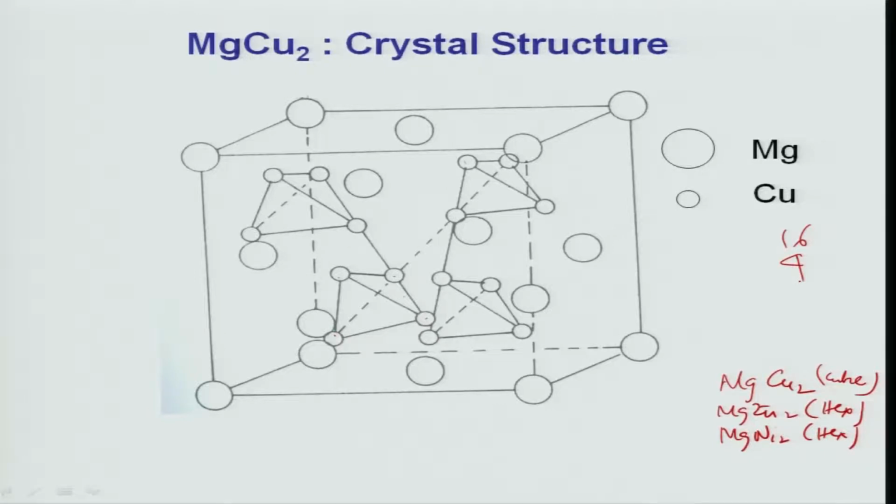But you have to understand that out of these 16 atoms, 8 atoms are for the unit cell, other 8 are not. So that is why it is 8 by 4, that is why it is MgCu2. Cu is 8 atoms and 4 atoms are magnesium. So this is the first type of structure, and there are many compounds like TiBe2, AgBe2 and BiAu2 that form this structure.